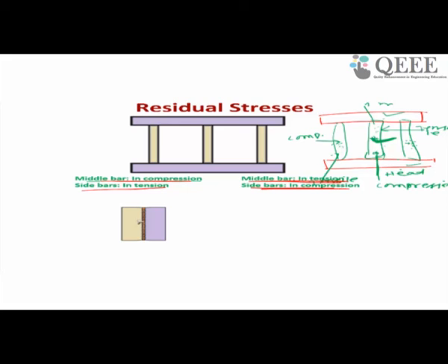The same phenomenon is happening in welding. When you weld 2 plates, plate 1 and plate 2, what will happen when you heat? This is your joining area. The joining area will try to expand, and the surrounding area will resist that expansion. As a result, compressive stress will be developed at this weld zone, and a tensile stress field will be developed in the side zone.